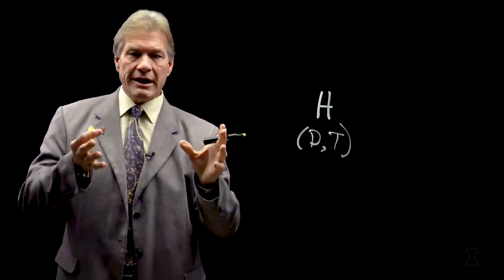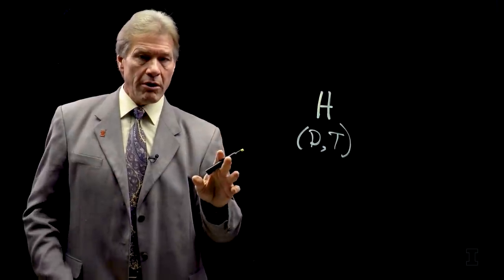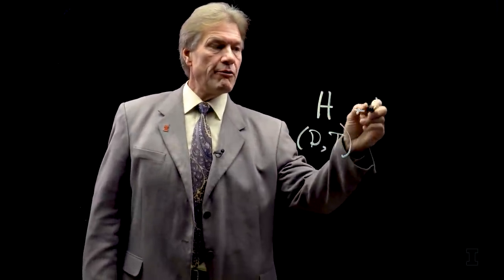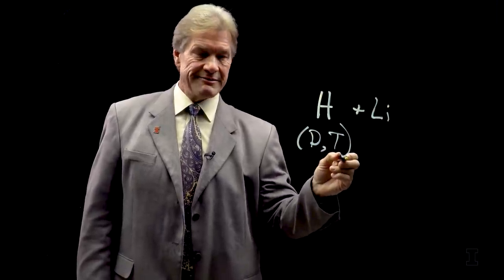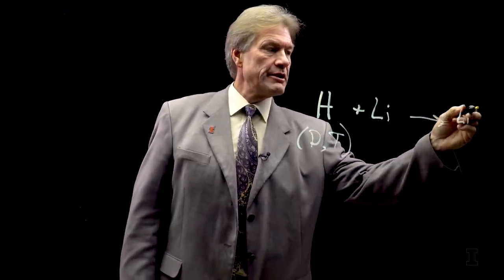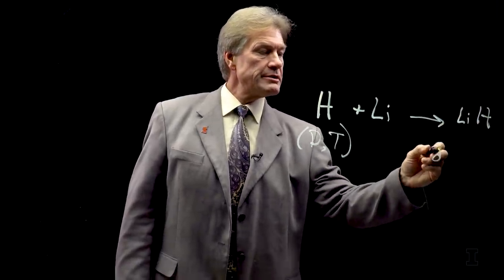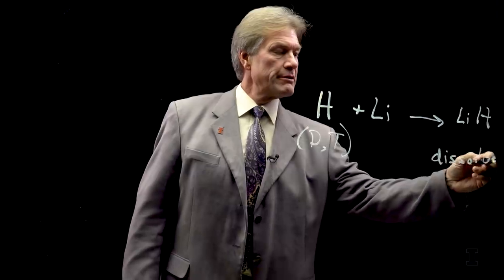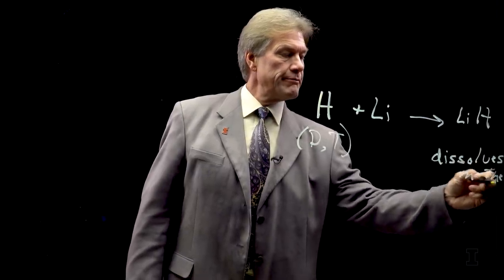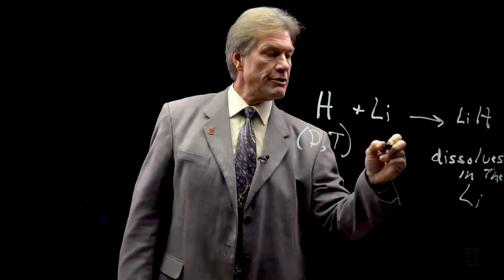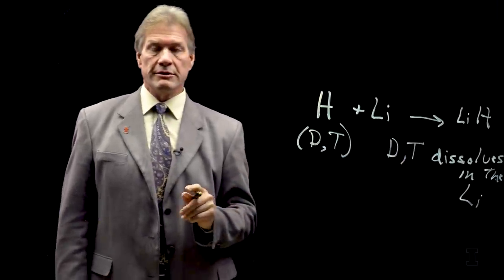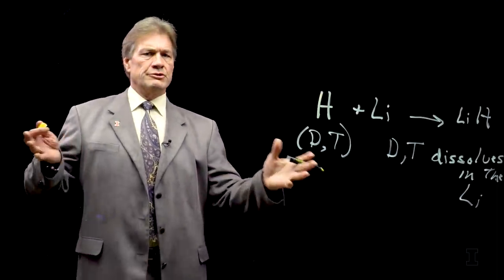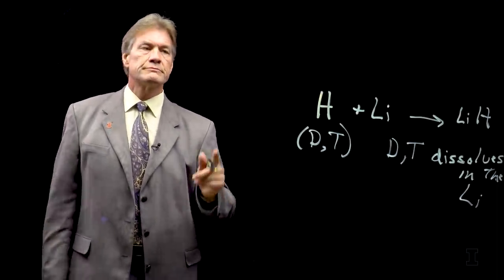The real advantage of lithium is because when hydrogen, the hot hydrogen, well, really deuterium or tritium that we're trying to get in a fusion device, when it hits the wall, if it hits a lithium wall, it sticks. Because either this forms lithium hydrides, or it simply dissolves in the lithium. The hydrogen, the deuterium, the tritium dissolves into the lithium. And you might say, so what? Who cares? We care.